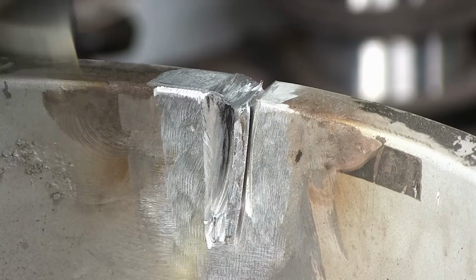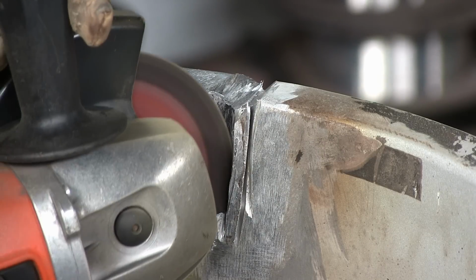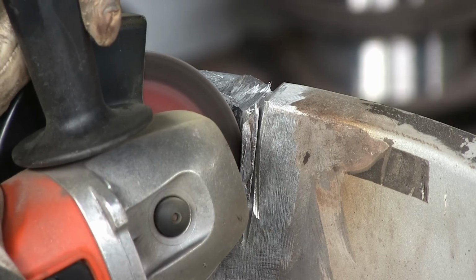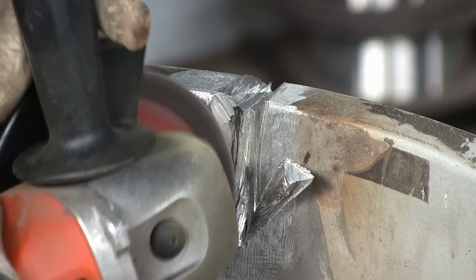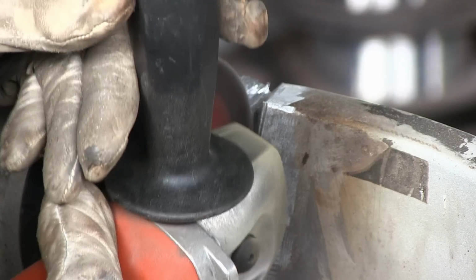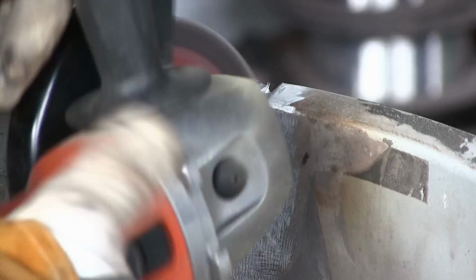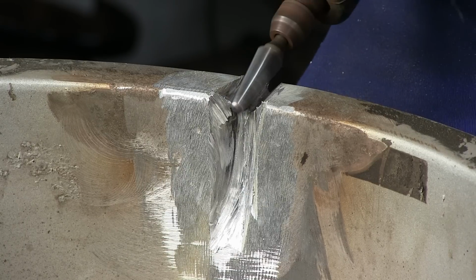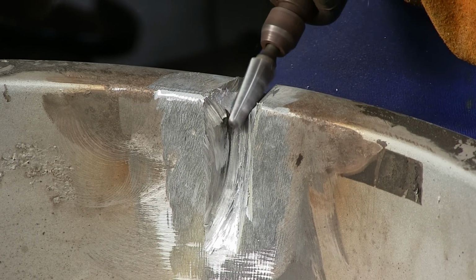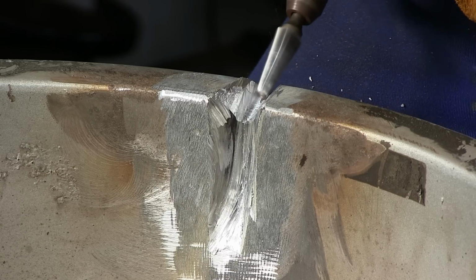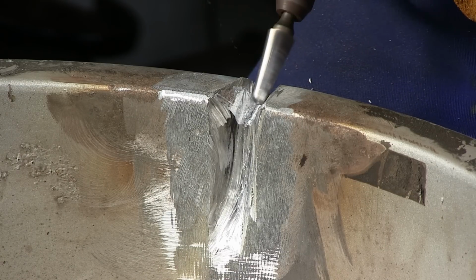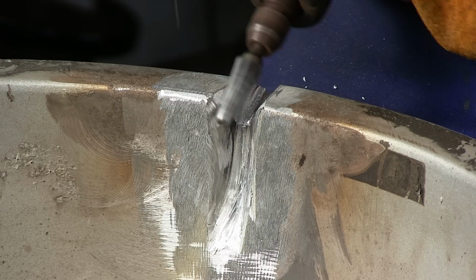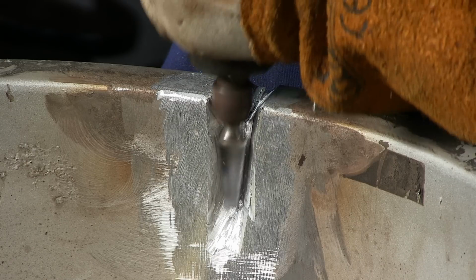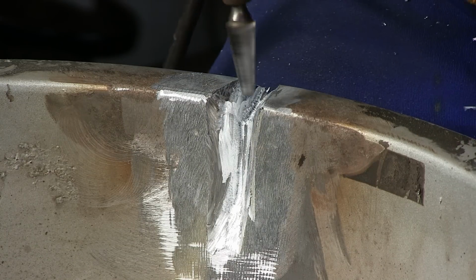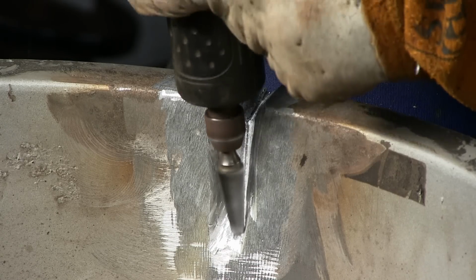So yeah, basically speaking, I'm cutting out that crack, and I'm cutting all material out so I can get right into clean metal, because as I mentioned before, the high thermal conductivity of aluminum is what's stopping you from penetrating really deep. Even if you run it at very high amperage, you will only penetrate so much, and depth of penetration is nothing compared to steel or stainless steel, because aluminum is about 4 times more thermally conductive than normal steel, and when you're trying to weld, it will just absorb heat like you wouldn't believe. And that's pretty much one of the main reasons why heat sinks, in applications for electronics and so on, use aluminum quite a lot.